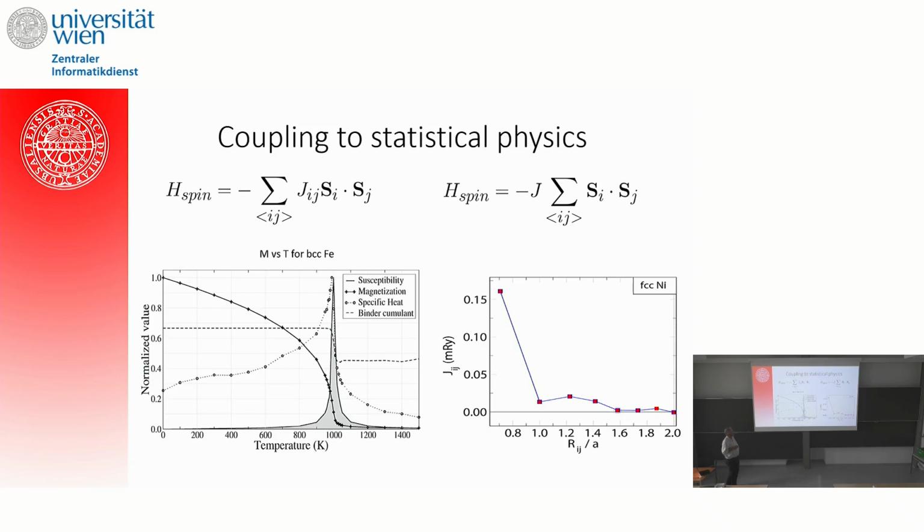You want to test, of course, if this makes any sense at all. And so we took these exchange interactions, put them onto a Heisenberg spin Hamiltonian and subjected that to regular elements of statistical physics and calculated the magnetic moment, normalized value, m over m0 versus temperature. And then we got this curve here. It's actually terrible at lower temperature, but it gives a fairly decent ordering temperature.